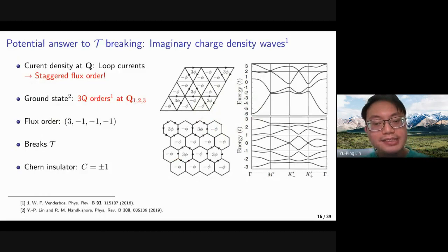So a potential answer to the time reversal symmetry breaking can be realized with an imaginary charge density wave. We have said that the imaginary CDWs are the current density modulations at a finite momentum Q. And on the lattice structure, it will correspond to a loop current. For each loop of the currents, we could define an auxiliary magnetic flux, which could be thought of as a spontaneous magnetic field. So it corresponds to a staggered flux order. You can think of it as a d-density wave in the square lattice cuprates, but now it's for the hexagonal lattice.